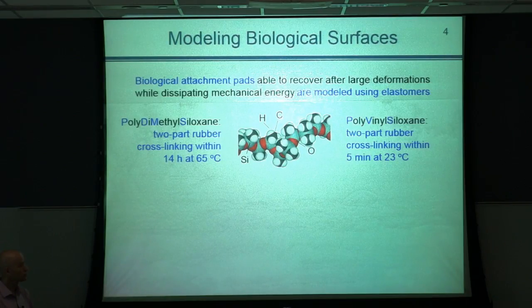Two materials that we usually use are PDMS, polydimethylsiloxane, which is a two-part rubber-like material that cross-links within several hours at a temperature that is a little bit higher than room temperature. And polyvinyl siloxane, which is also a two-part rubber-like material that is used by dentists as a dental wax to copy what we have in our mouths in order to make prosthetic fixtures. And this material polymerizes within a really short time, 5 minutes at room temperature.